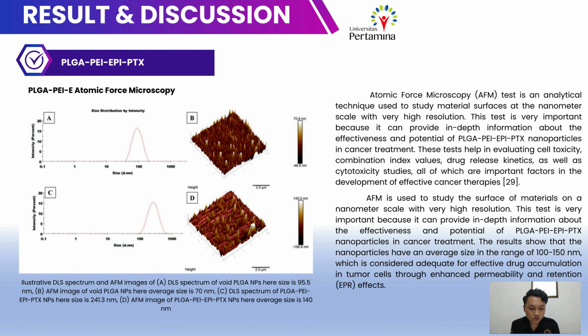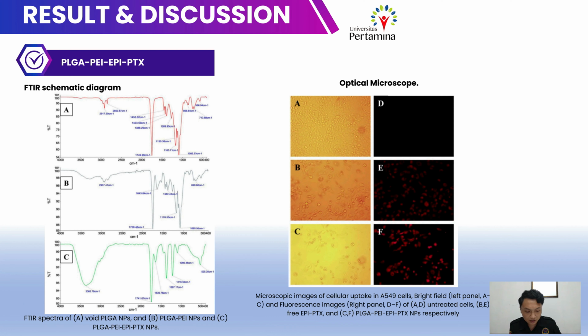AFM is used to study the surface of material on a nanometer scale with very high resolution. This test is very important because it can provide in-depth information about the effectiveness and potential of PLGA-PEI-EPI-PTX nanoparticles in cancer treatment. The result shows the nanoparticles have an average size in the range 100 to 150 nanometers, which is considered adequate for effective drug accumulation in tumor cells through the enhanced permeability and retention (EPR) effect. To support the AFM result, an FTIR test was conducted with the following result.